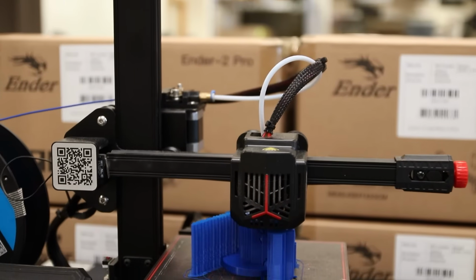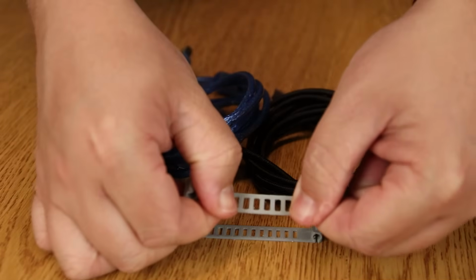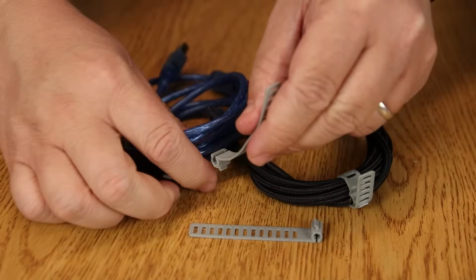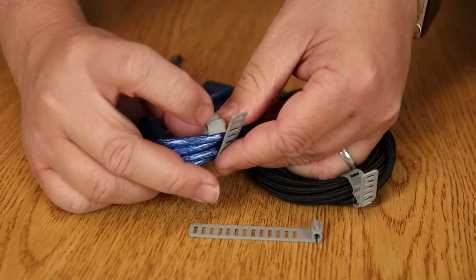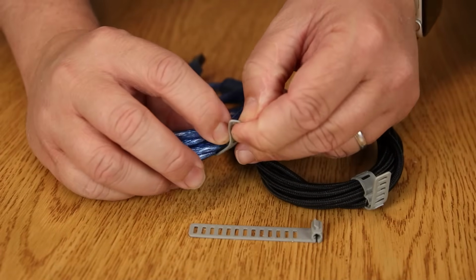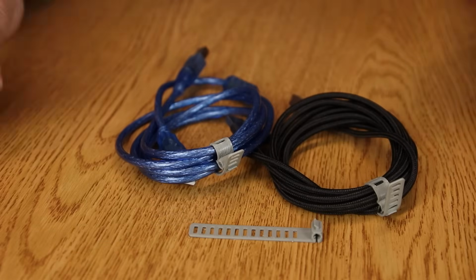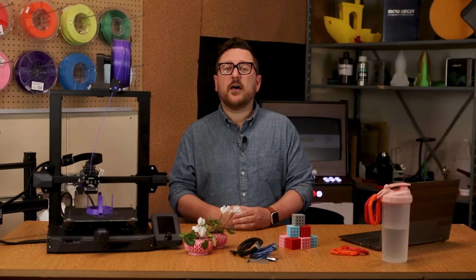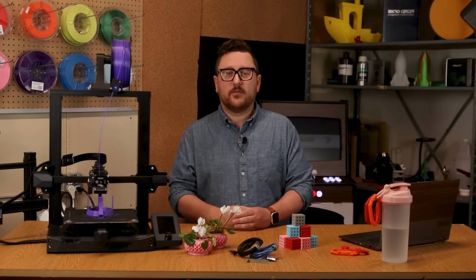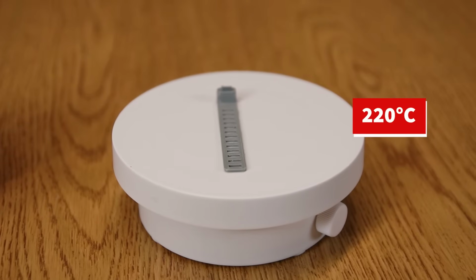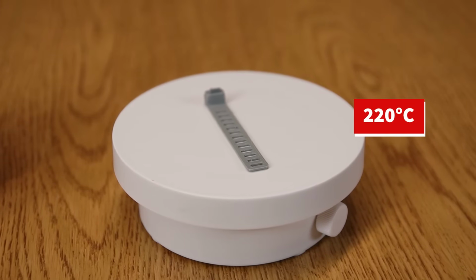For TPU, we chose to show off its flexibility by printing these small cable ties. The interesting thing about this print is that there's actually a customizer on thingiverse.com allowing you to modify the size and number of holes to fit your needs. We ran these at 220 degrees Celsius for the hot end and 42 degrees for the heated bed.